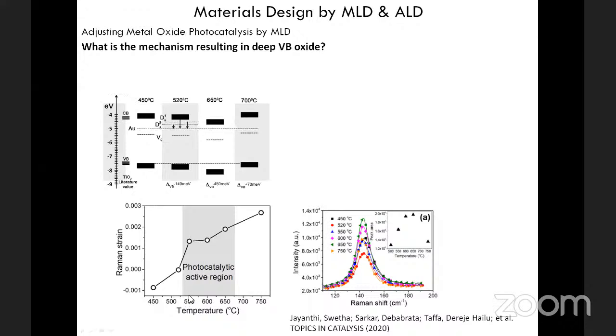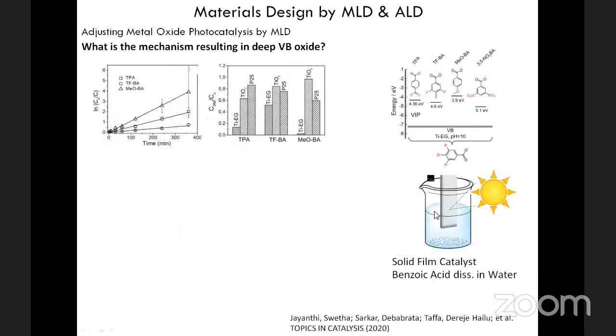And indeed, what we saw that for this activity region where anneal temperatures show increased activity, which correlate with the shifts also, indeed there is a Raman strain, what we call Raman strain. So from the Raman data, we could deduce that there is an inherent strain in the oxide. And this started quite a long journey where we not only looked on how better our films performed compared to others, but we decided to do a more systematic study and take substituted benzoic acid and study the kinetics and how those correlate with the electronic parameters like ionization potential, charge density, dipoles, and so on, and quantify all this.